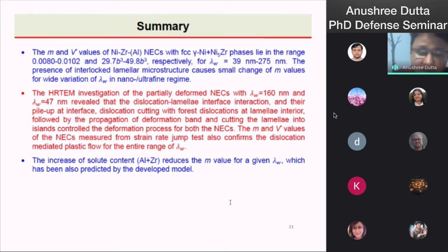And the HRTEM investigation of the partially deformed NEC revealed that the dislocation and lamellar interaction and their pile-up at the interface, dislocation cutting through the lamella, followed by the propagation of deformation band and cutting the lamellae into islands control the deformation process for both NECs. The m and V values of the NECs measured from the strain rate jump tests also confirm the dislocation mediated plastic flow in the entire range of lamellar thickness.